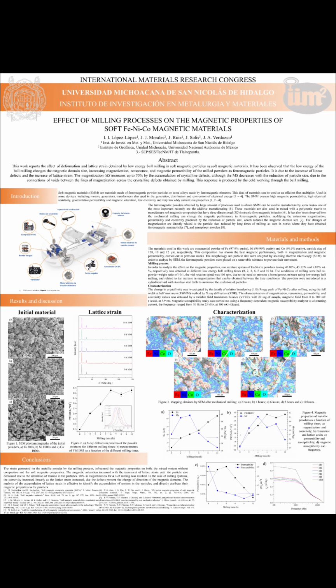In this case, the iron particles accumulated deformation until 6 hours of milling. At this step, they began to fracture, reducing the particle size as milling time increased. Although this reduction was not significant, since it is known that to reduce the size in a major manner by mechanical milling, times longer than 20 hours at 300 revolutions per minute are necessary.